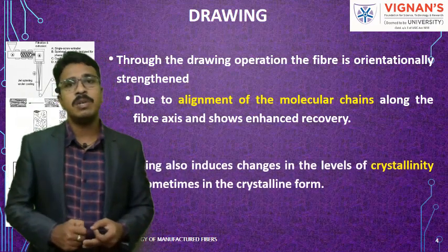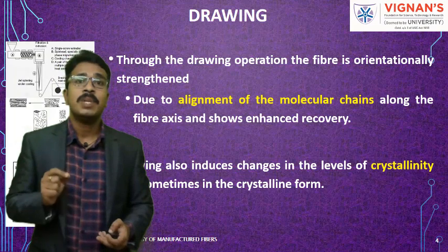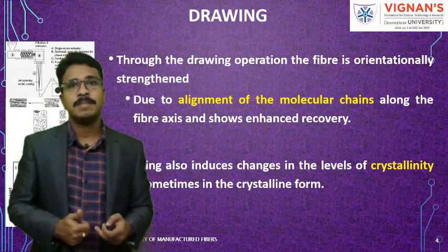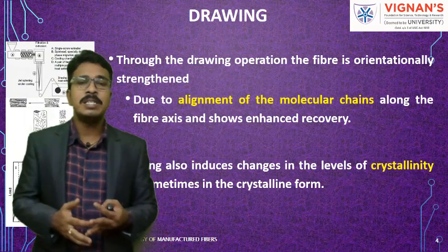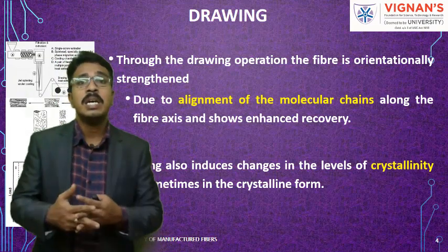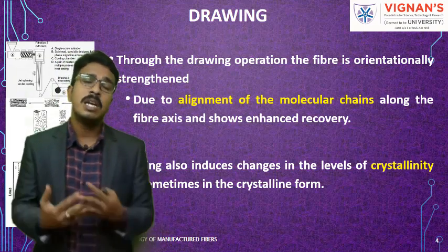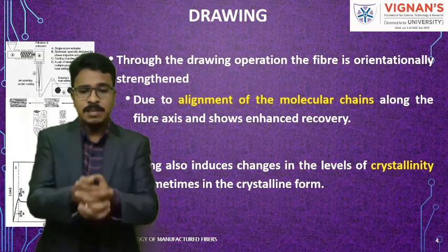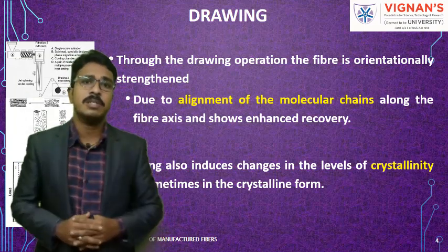The drawing also induces changes in the levels of crystallinity. If orientation takes place to a high degree, the polymer becomes more crystalline, that is, it has very highly compact regions.